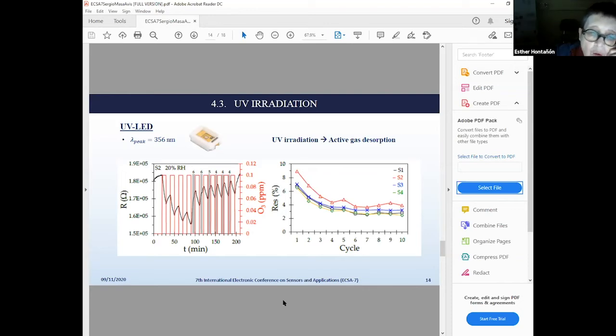to recover the baseline and also to see stability in the response. You can see here the response for the different cycles. In the first cycles, the sensor was not illuminated or irradiated, so you can see this decrease in the sensor response. Once the UV is activated during the recovery phase or the gas desorption phase, the resistance baseline is recovered, and then the response is much more stable. We reach a value of about 4% for 100 ppb of ozone.